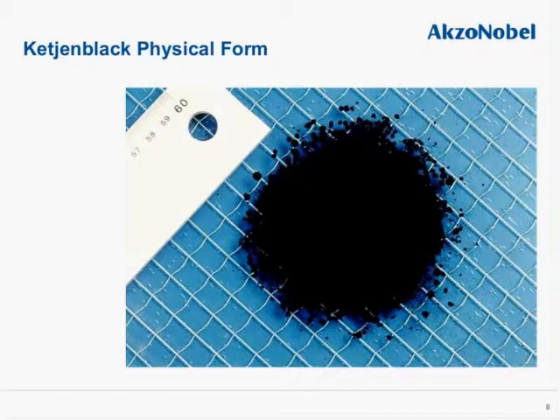Ketjenblack physical form: as very well known, Ketjenblack is a fine particulate and can be extremely dusty. And the way we control this dustiness is by turning it into a pelletized product. The pellets have a low crush strength. They are about 2 to 3 millimeters in size, and by doing that, we not only prevent the dusting, but we ensure that the product is readily mixable in the polymer matrix by ensuring a better wettability of the product.